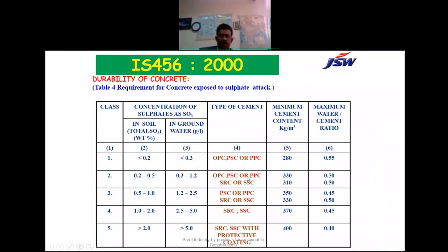And similarly, IS 456:2000, considering the durability parameters, exposure conditions when sulfates and chlorides are there, Table 4, clearly mentions the usage of slag cement when we have both chlorides and sulfates in the concrete.